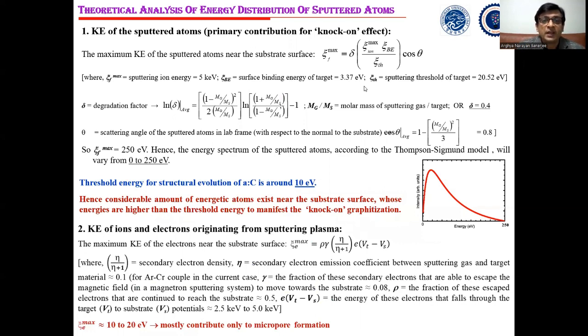Now, when we did the theoretical analysis of the first contributor, which is the kinetic energy of the sputtered atoms, we observed that the energy of the sputtered atoms varies from 0 electron volt to almost 250 electron volt. On the other hand, the threshold energy for this knock-on graphitization or structural evolution of the amorphous carbon is 10 electron volt. Therefore, we can say that a considerable amount of energetic atoms exist near the substrate surface whose energies are higher than the threshold energy to manifest the knock-on graphitization.